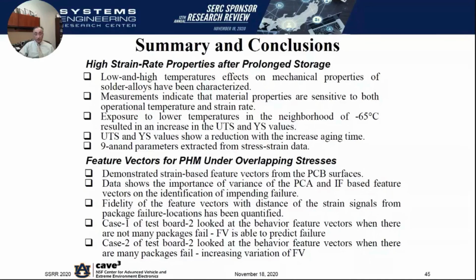So yeah, that's a great question, James. Actually, that's a more complex case, where we would have multiple exposures of thermal storage and multiple exposures of high strain rate harsh environments. In our case, what we assumed was there was the initial storage when the assembly was pristine, it was new, it was stored prior to deployment, and once it was deployed, it basically was used till end of life or wear out. But you're correct that may not be the case. Assemblies may come out of storage, they may be deployed, they may go into storage, and then they may be deployed again. And that's a much more complex case, which requires us to actually do something called cumulative damage assessment. And that's somewhat further down. We do not have even base damage relationships in this particular space. So that's a technology gap under overlapping stresses.